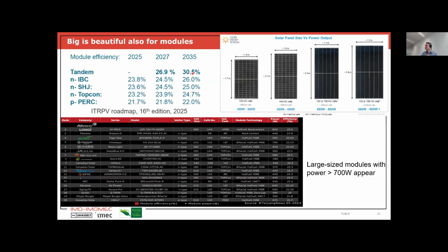And here you see the projected efficiencies by 2035. So there is still some room for improvement for the TOPCon, heterojunction and IBC to values, let's say, somewhere between 25 and 26. But then if we really want to make a big step forward, we will have to go to tandem devices. Tandem devices at the moment still need a lot of R&D. They are not really upscalable enough yet, not stable enough yet. But this is really the way forward for the future.